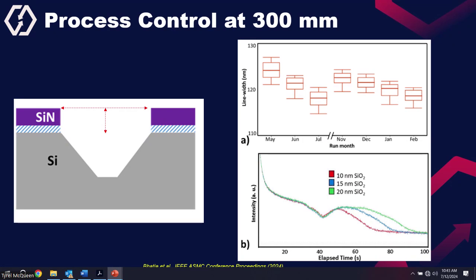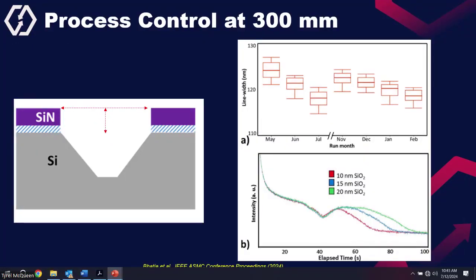After that is established, we use an anisotropic etch, which exposes the 111 planes. Because this is a wet etch process, there is no silicon damage created at the sidewall, which is an important consideration for quantum devices. Because this is due to the crystal nature itself.